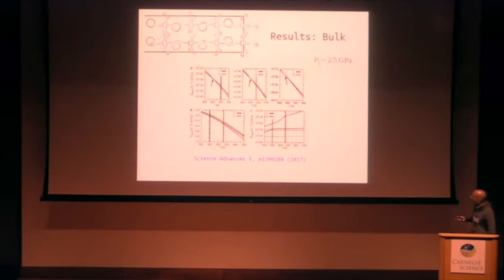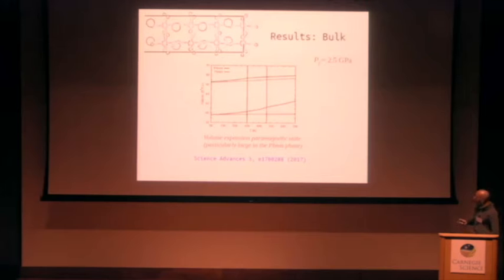First of all, we realized that anytime the tetragonal or the orthorhombic phase became paramagnetic, its Gibbs free energy suffered a change of slope so that it became energetically more favorable, right? We looked into the Helmholtz free energy and enthalpy contributions to the Gibbs free energy, and we realized that the term with the bigger effect, responsible for these changes in the slope, was the enthalpy contribution, right? The reason is that anytime the system became paramagnetic, the volume of the system expanded. So the enthalpy, which has a pressure times volume term, gets worse, right? And in the special case of the non-polar phase, this is very extreme. The system just gets higher and higher in volume, right?